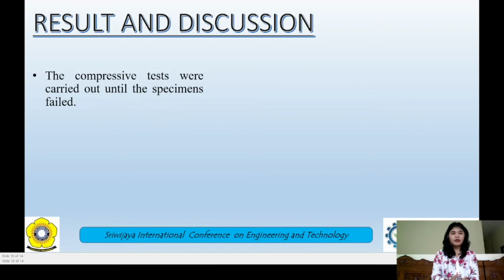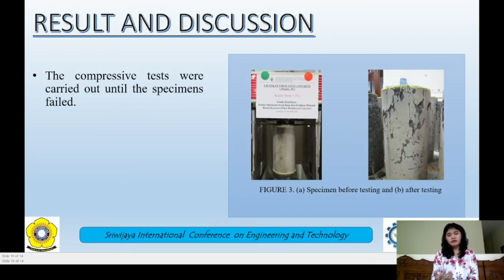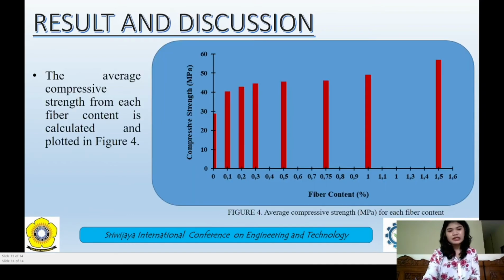The third point, result and discussion. The compressive tests were carried out until the specimen failed. We can see figure 3 showing the specimen before testing, and the second one, the specimen after testing. The average compressive strength for each fiber content is calculated and plotted in figure 4. It can be seen from figure 4 that the addition of steel fibers increases the compressive strength of concrete. The effect of the fiber content is significantly visible when the fiber increases from 0% up to 0.1%. The increase in compressive strength continues with the increase of fiber content. However, the increase of strength is relatively small for specimens with fiber contents of 0.1% up to 1%.